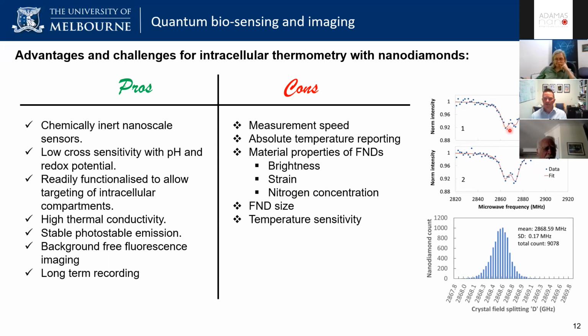And you can see, when you're looking at different nanodiamonds, that the crystal field splitting position is very different for lots of different nanodiamonds. So we looked at thousands of nanodiamonds, and the crystal field splitting moves all over the place due to the fact that there's different strain in these materials as well. So that's another challenge to think about in terms of improving the utility and the sensitivity of these sorts of systems. And also the size is an interesting thing to think about.